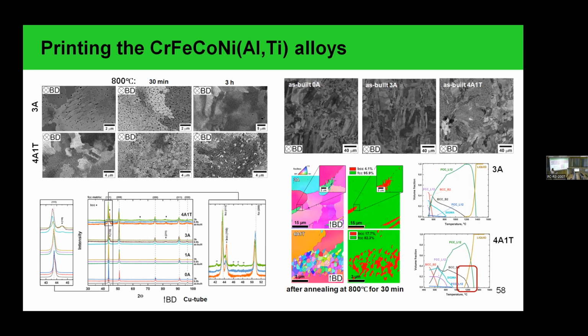So to explain this phenomenon, we prepared two phase diagrams, for the material with aluminum and for the material with aluminum and titanium, and observe the difference that in case of the materials with aluminum only, from the liquid, we see the formation only of the FCC phase. And only after, the BCC forms from this solid FCC phase. In case of the material with aluminum and titanium, we see the simultaneous formation from the liquid of two phases, BCC and FCC, which explains the small grains of these two phases in the as-built material.